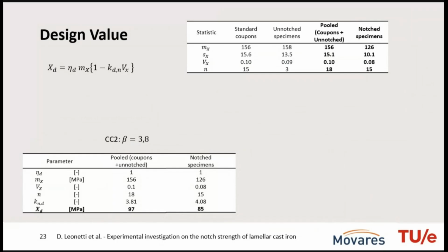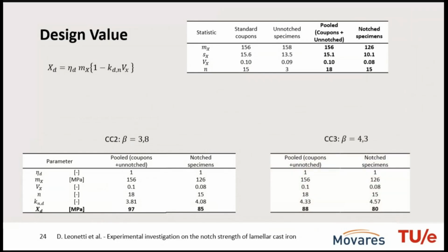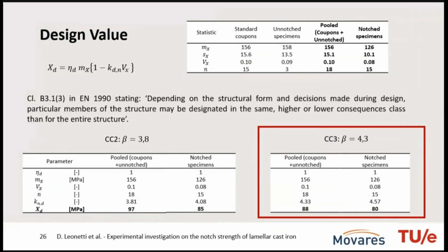To cut it short, essentially, we came up with these two design values for the strength, for notched and unnotched. And for consequence class 3, instead, we came out with slightly lower values. So then we followed what the Eurocode 0 states: you can decide for a part of the structure to apply a different consequence class than what would be considered for the entire structure, depending on the design considerations. In that case, we considered a higher consequence class, so a bit more safety, because in fact the design did not take into account the presence of defects. If it had, when they designed the column, then consequence class 2 could be desirable. But we went for a bit higher safety level.